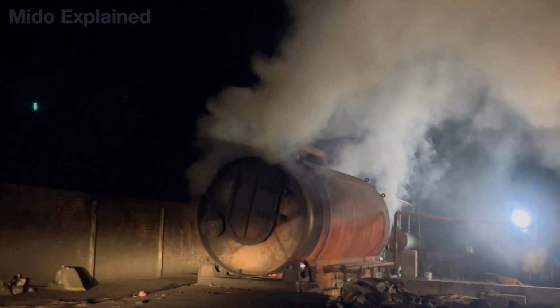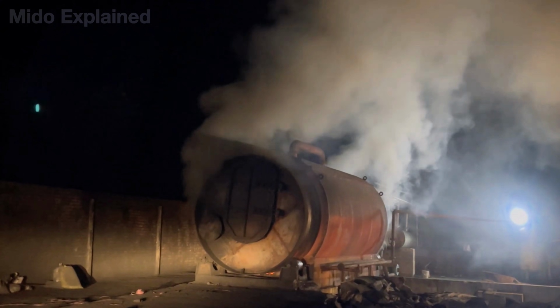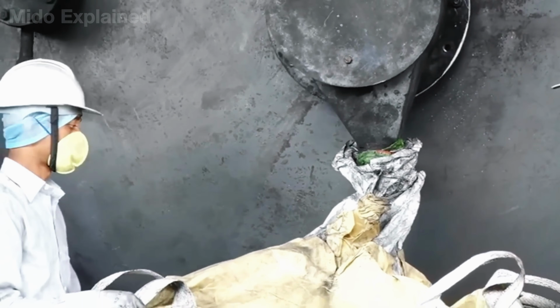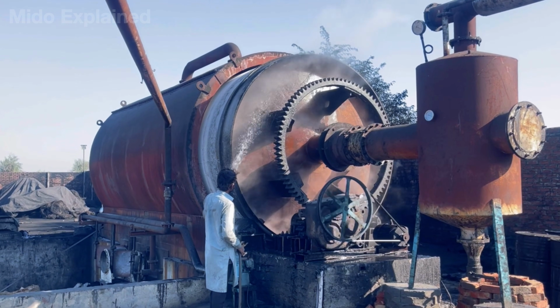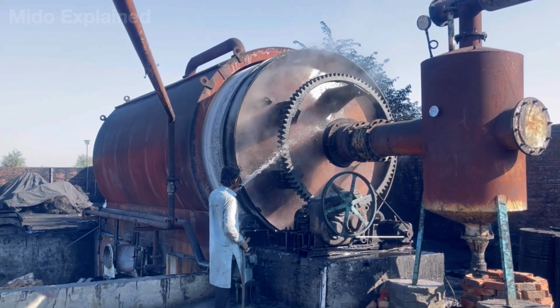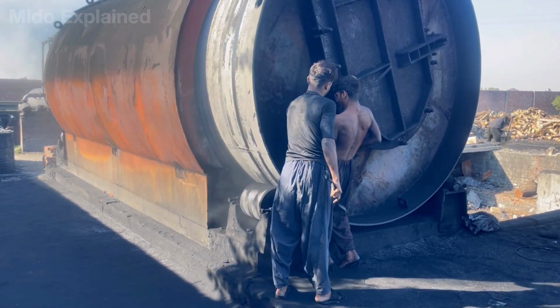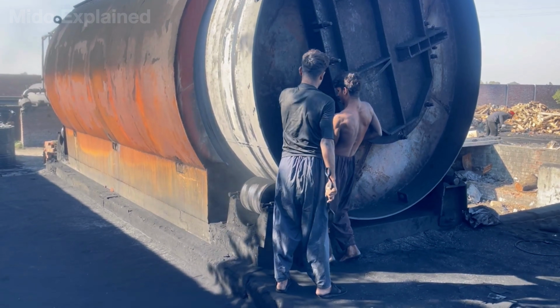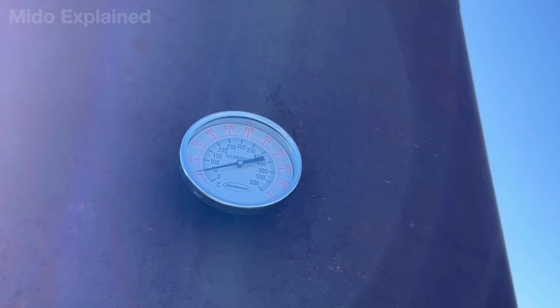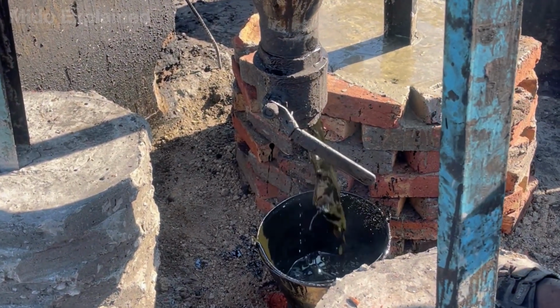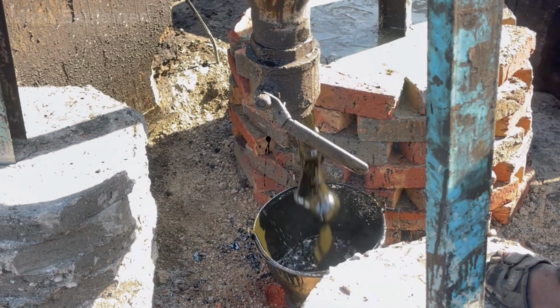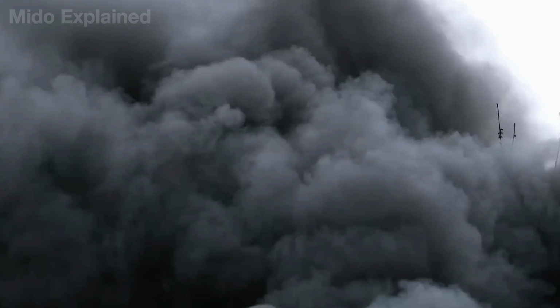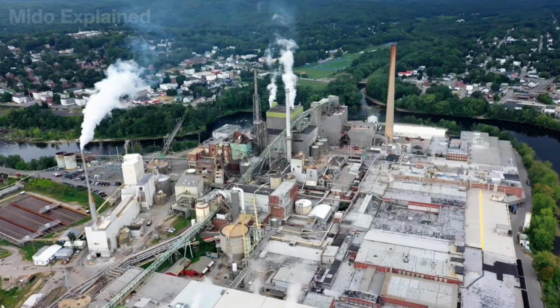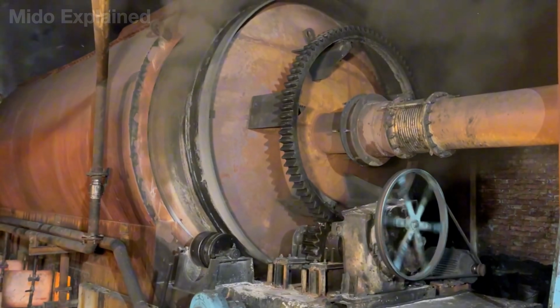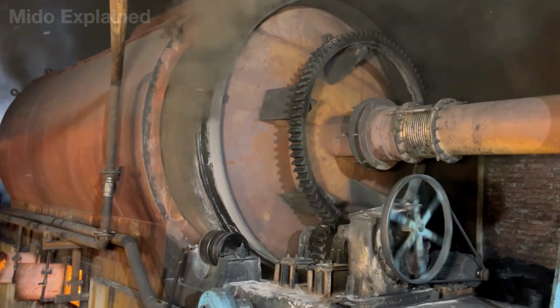The generated gas is usually returned to the furnace to maintain heat, reducing the need for external fuel. Meanwhile, carbon black, which accounts for about 30% of the tire's weight, is recovered for use in the production of rubber, plastics, and paints. This technology has already been implemented in hundreds of factories in China. However, if the exhaust gas treatment system does not meet standards, the pyrolysis process still risks releasing toxic compounds into the environment.